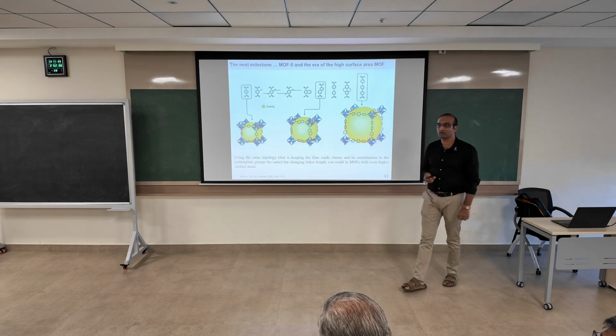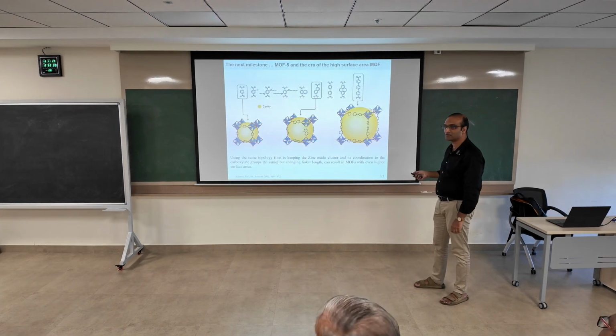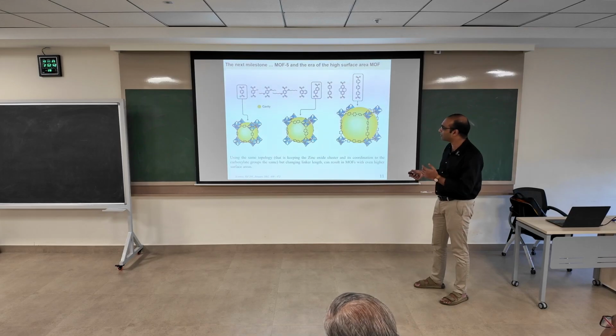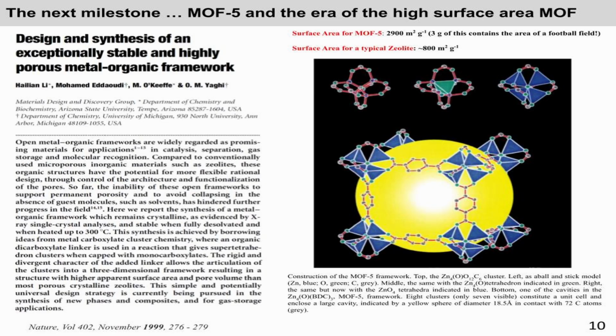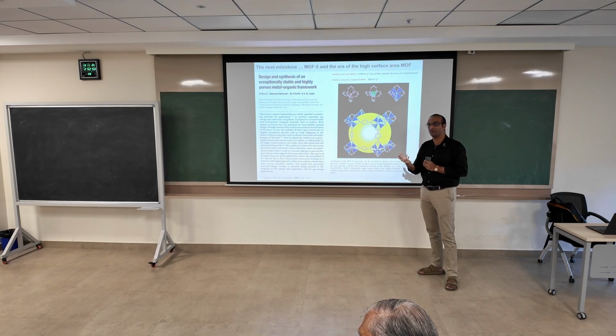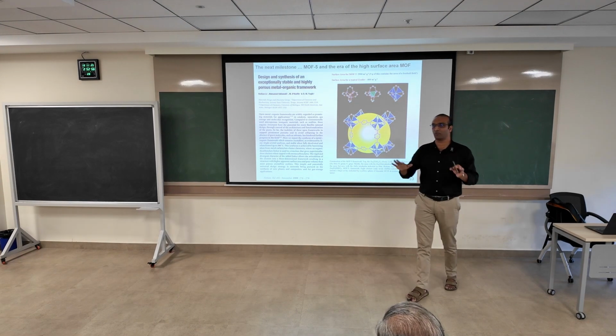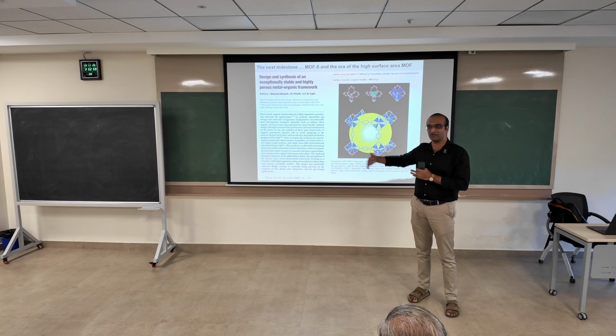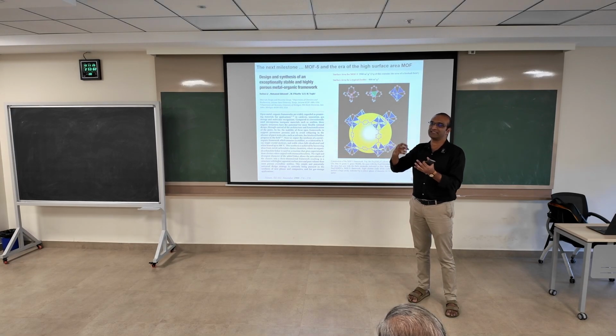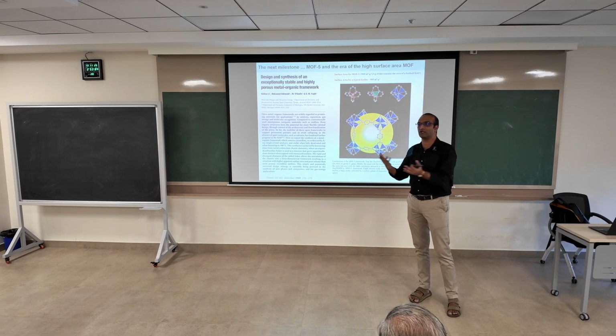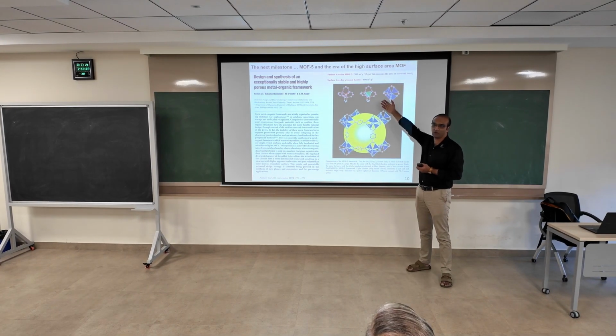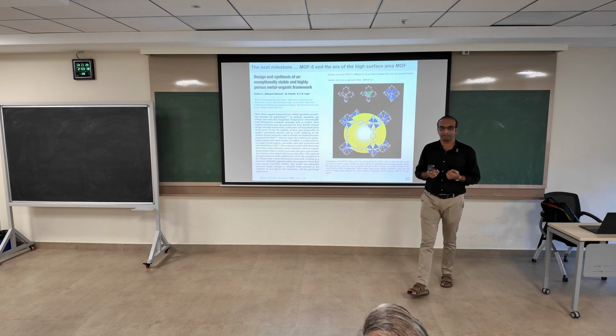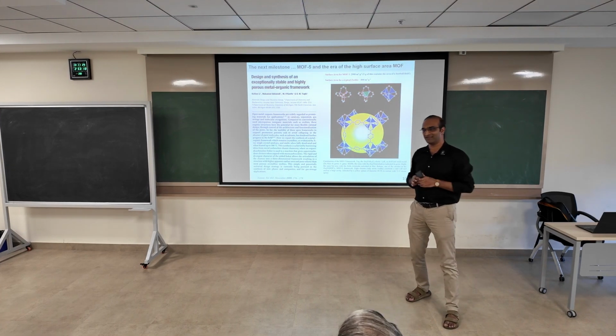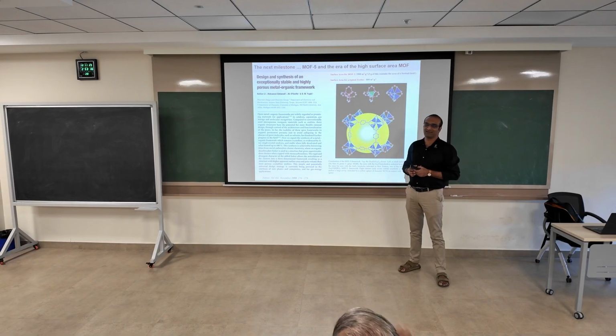What is the surface you're talking about? Can we see it on this image or not? Which one? The surface? You're saying it's as big as a football field. Oh yeah, I mean you can't see it on this. Basically what I'm saying is this pore, right? If I take 1 gram of this particular material, the kind of volume that it holds inside, the whole MOF, 1 gram of that MOF, will be equal to the surface area of a football field. You convert the space within that volume, those pores, into surface area, and it would be the equivalent of 1 football field. What you're saying is if you were to adsorb a gas and treat the surface that it is sitting on, that area would be... Yes.